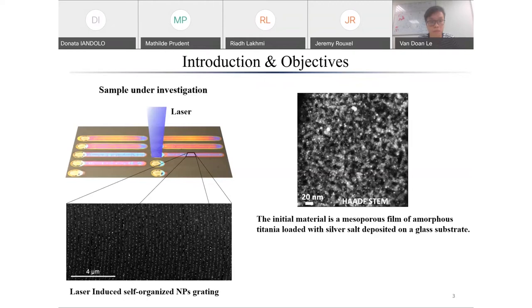So under the laser processing, we have three main transformations of the sample, which are the organization of the nanoparticles, the radius distribution of the nanoparticles, and the evolution of the film. But in this study, I will show you that the color is mainly due to the film formation.